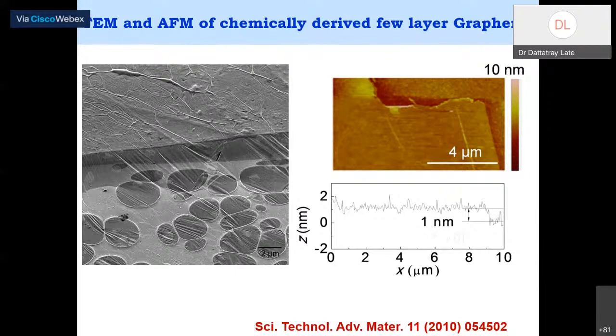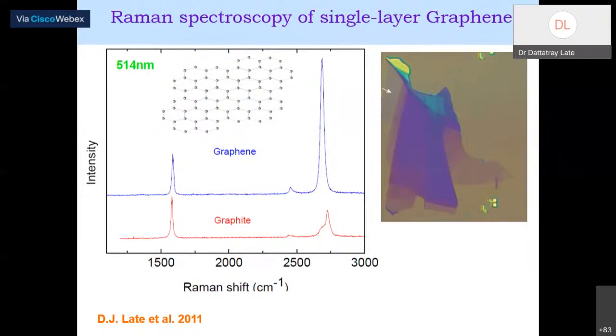You can see this is the graphene sheet kept on the TEM grid. You can see every nice layer that has been seen here. Of course, we can do AFM, atomic force microscopy, where we can find out the thickness of this particular graphene layer grown by CVD. We see 1 nanometer thickness, which means there are nearly three layers of graphene, right? Of course, one of the most powerful techniques to characterize graphene is Raman spectroscopy.